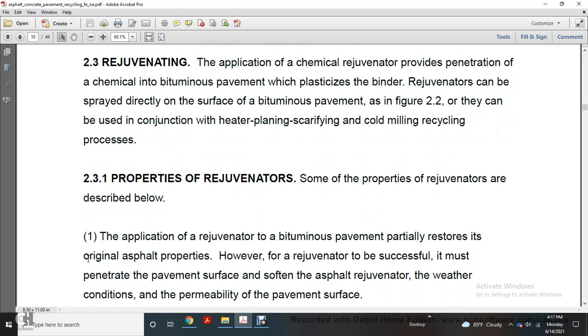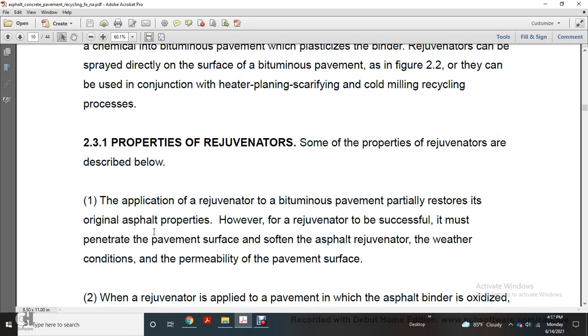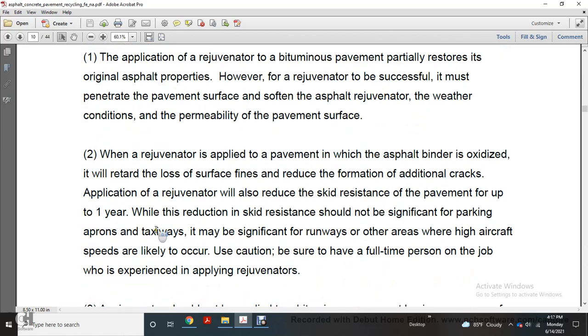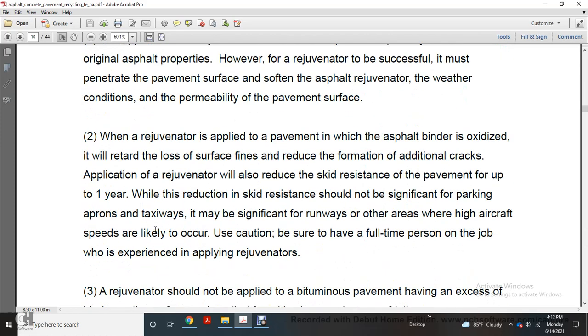1. The application of the rejuvenator to the bituminous pavement partially restores the original asphalt properties. However, the rejuvenator must be successful in penetrating the pavement surface into the asphalt, depending on weather conditions and the permeability of the pavement surface. 2. When the rejuvenator is applied to pavement where the asphalt binder is oxidized and matured, the loss of surface fines is reduced, reducing the formation of additional cracks. The rejuvenator will also reduce skid resistance of pavements for up to one year. The reduction of skid resistance shall not be significant on aprons and taxiways, but may be significant for runways and other areas with high aircraft speed.